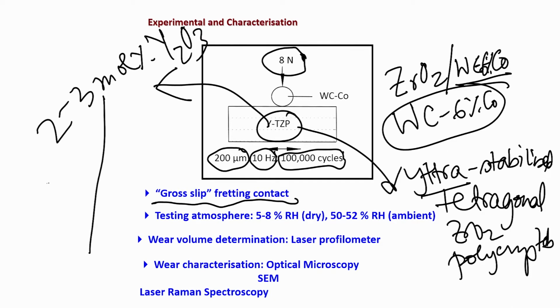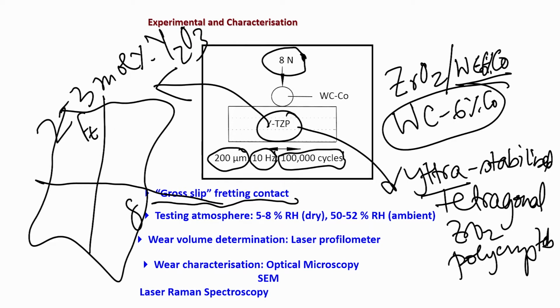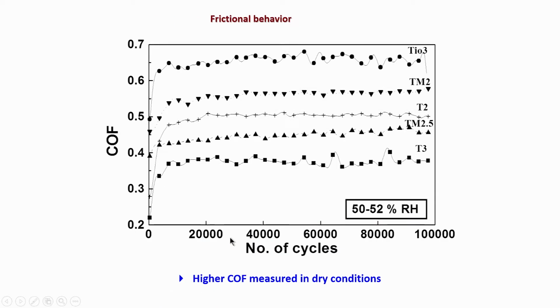Gross slip fretting contact means if you plot tangential force versus displacement, it has a very wide loop, a larger loop, and that is what is expected in many of the applications with severe operating conditions. Testing atmosphere, we have used dry and ambient conditions, and then wear is characterized using microscopy as well as laser Raman spectroscopy. Now, this is at ambient humidity conditions, you can see.